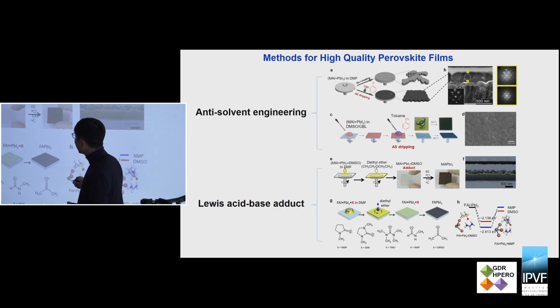Usually when you make the perovskite film, while spinning, you drop some anti-solvent, which does not dissolve the perovskite phase but dissolves some organic solvent. The anti-solvent engineering was proposed by Professor Sang Il-seok and also Professor Yi-Bing Cheng. And we proposed the Lewis acid-base adduct method. It's similar to anti-solvent engineering, but we deliberately induce the Lewis acid-base adduct.